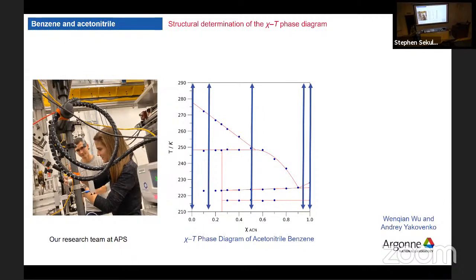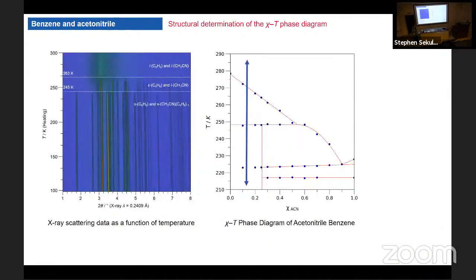That's why we went to Argonne and we collected data within just a couple of hours, and we covered all of the phase regions. Okay, so here I will present just one set of those data and what we can learn from it. So we are going here, and we're cooling down. As we are cooling down, we are passing through all of these phase regions, and we're collecting data. This is how the data looks. So here is the temperature scale. And here is the 2 theta angle. The 2 theta angle, as you know, is the signal from the X-rays, and these are the bands.